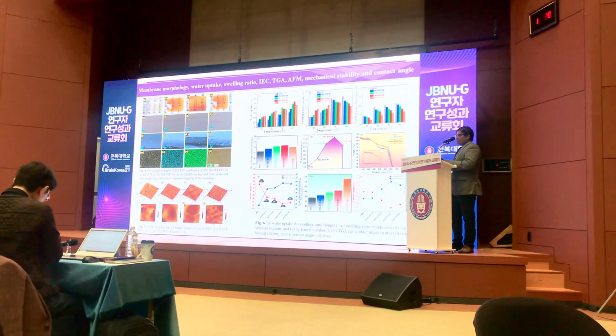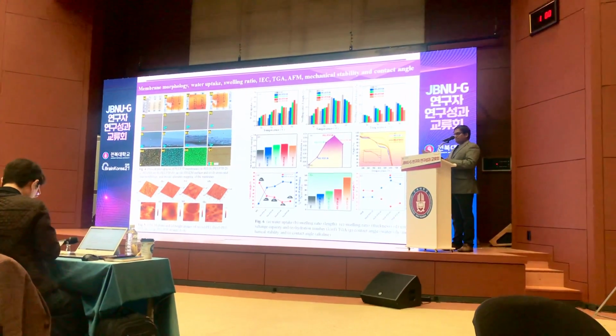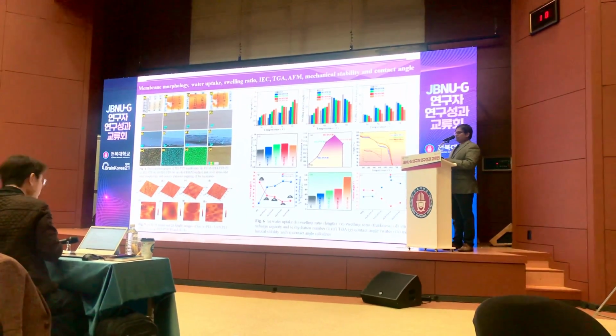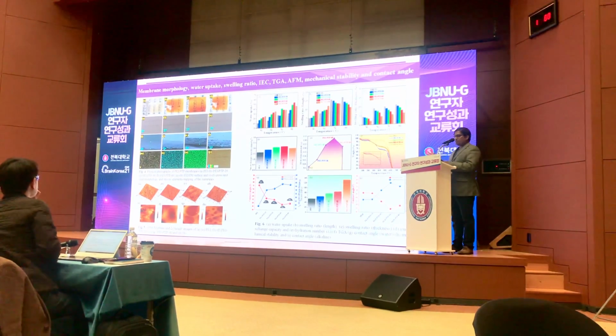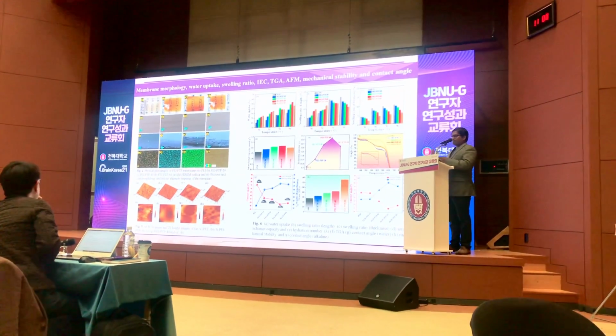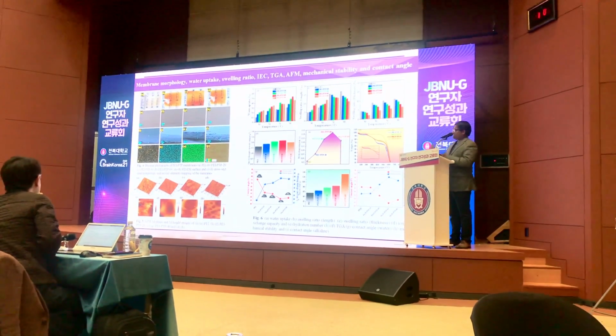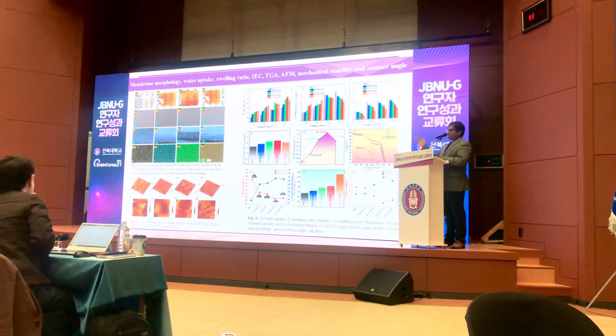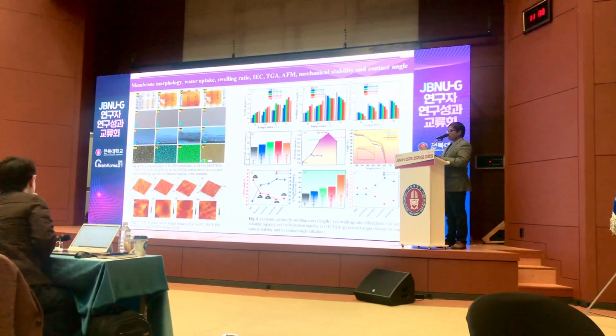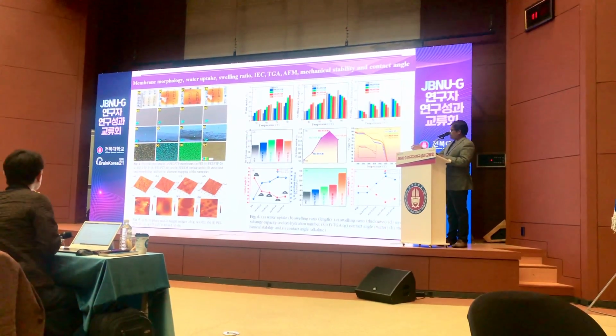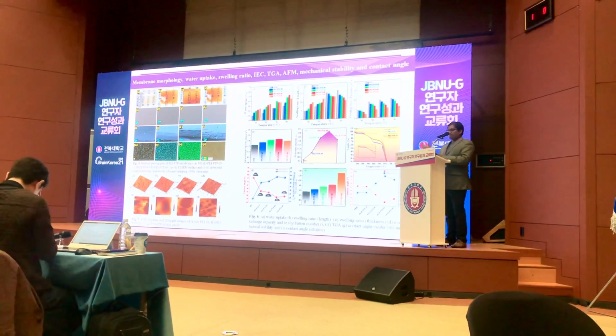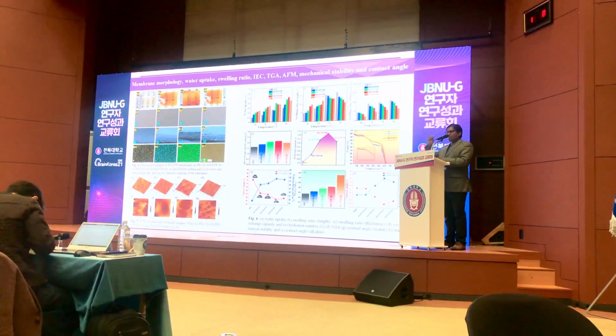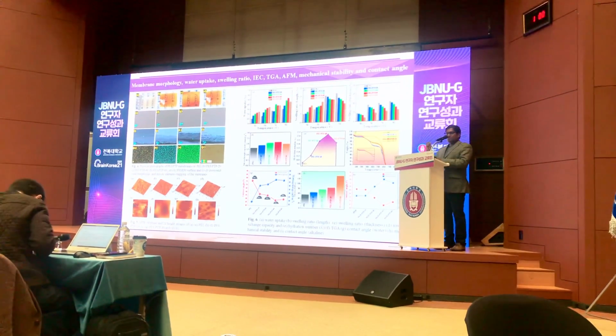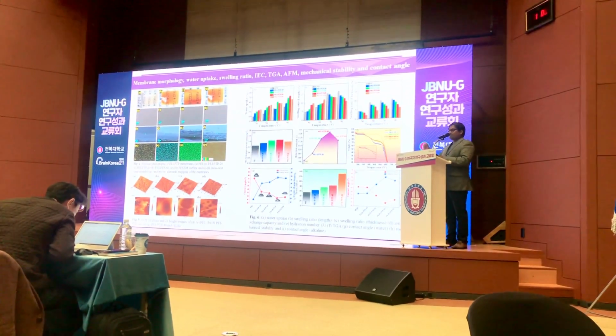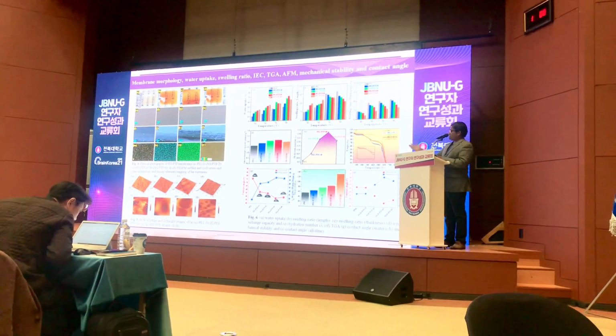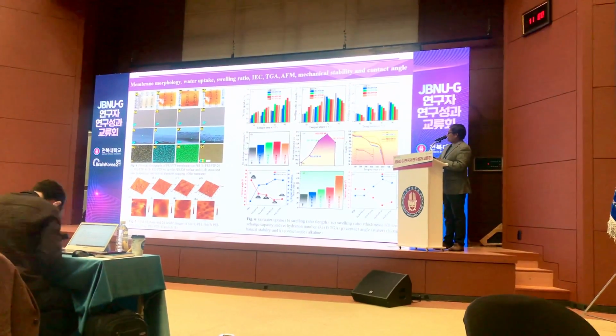And then these are the basic physical studies of the electrolyte. We have to study the morphology. We have to confirm there are no holes, so that there is no crossover between the hydrogen and oxygen gases. The FESEM analysis confirmed there are no pinholes in the membrane. And I also confirmed the microphase separation. When there is microphase separation, the ion mobility will be really good. If the ion mobility is good, it will have very good conductivity and fuel cell performance. So all these AFM studies also confirm very good microphase separation.